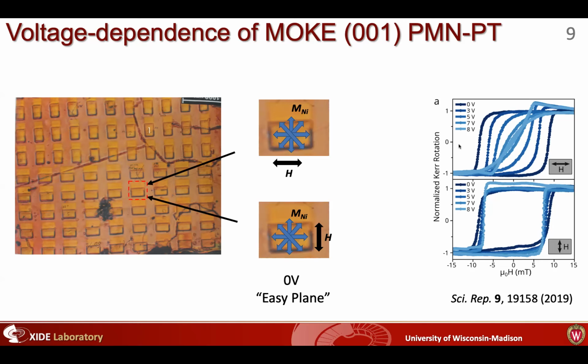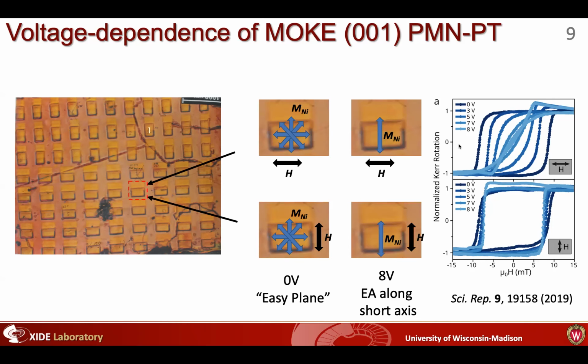And then as you apply a voltage to get to the lighter blue colors, along 0 degrees, we see a transition from this easy plane anisotropy to a hard axis. And then 90 degrees rotated to that, it even becomes a little bit more square. So what that tells us is our as grown easy plane is then going into an anisotropy where the nickel wants to prefer the short axis of this particular rectangular electrode. And we can kind of continuously induce that anisotropy with the voltage.